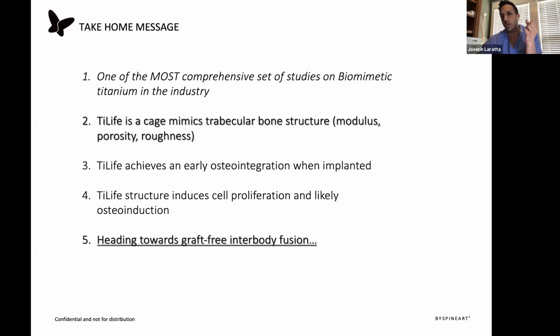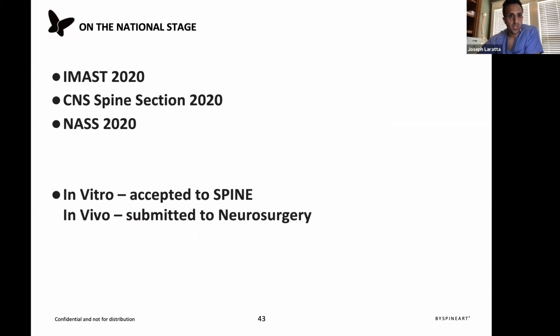Well, this is really comprehensive, right? So we looked at in vitro and in vivo for biomimetic titanium. When you mimic trabecular bone structure in terms of modulus, porosity, and roughness, there is likely things that are going on in terms of cellular proliferation, changes in morphology, differentiation into osteoblast, and early integration. And I think what this is leading us to is, can we eventually get to this technology becomes so good that bone graft and biologics are not necessary?